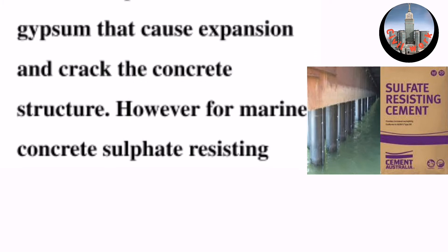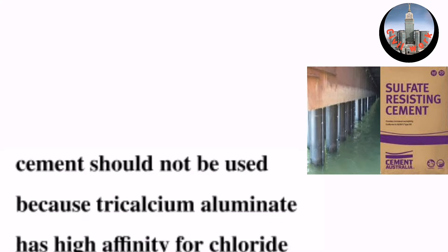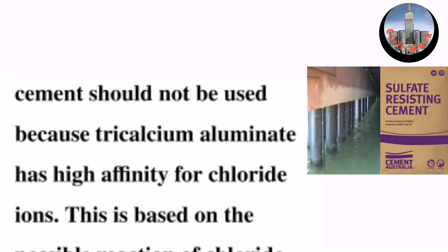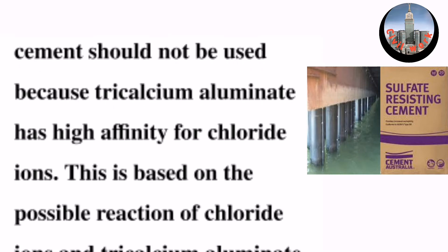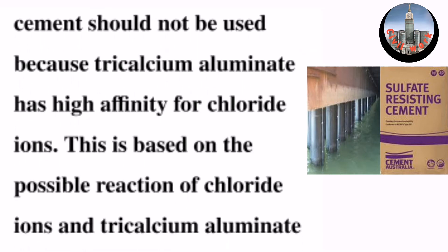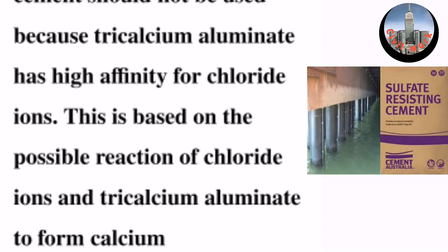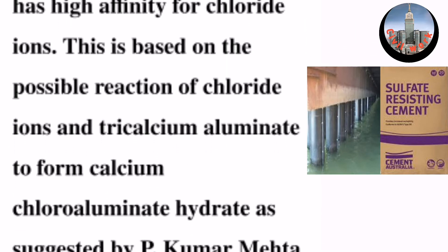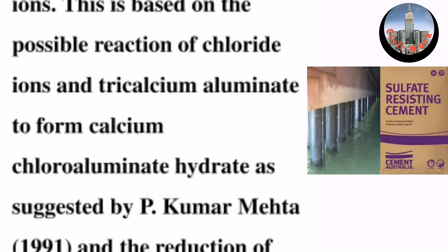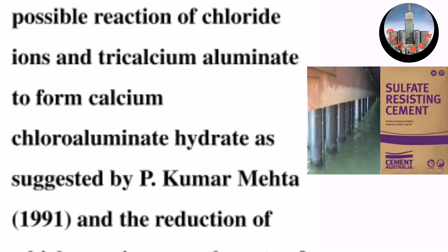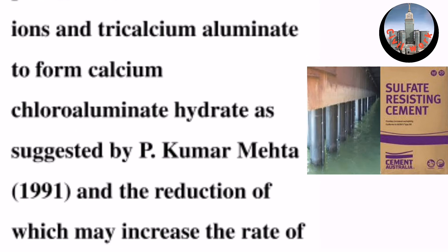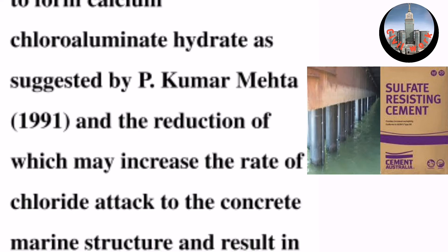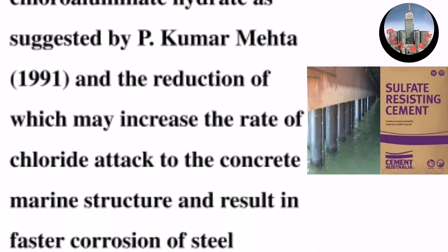However, for marine concrete, sulfate-resistant cement should not be used because tricalcium aluminate has a high affinity for chloride ions. This is based on the possible reaction of chloride ions and tricalcium aluminate to form calcium chloroaluminate hydrate, as suggested by P. Kumar Mehta (1991). The reduction of tricalcium aluminate may increase the rate of chloride attack to the concrete marine structure, resulting in faster corrosion of steel reinforcement in marine structures.